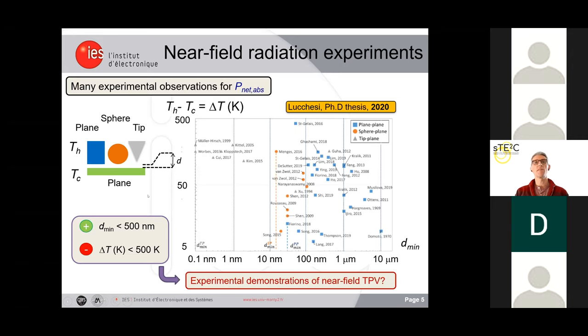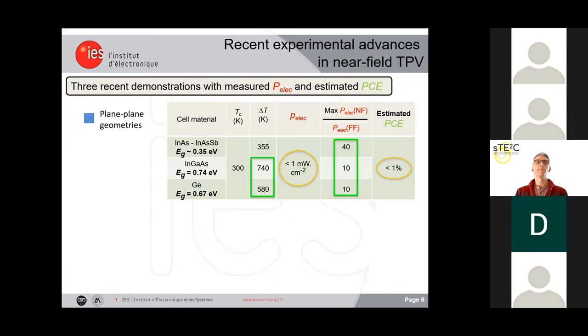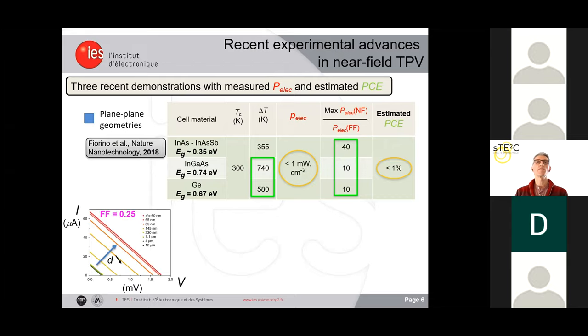So the question is, given that, is it possible to make an experimental demonstration of near field TPV? Well, the answer is yes. So there were three recent demonstrations with plane geometries. For the first one, indium arsenide was used with a low band gap, and you see the evolution of the IV characteristics as the distance decreases. So with that, a near field enhancement of 40, which is defined by the maximum electrical power in the near field to the electrical power in the far field, was achieved.